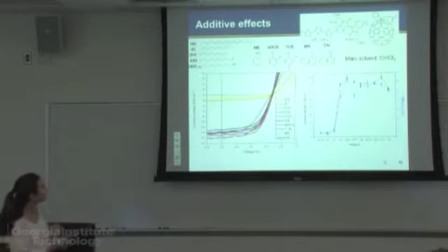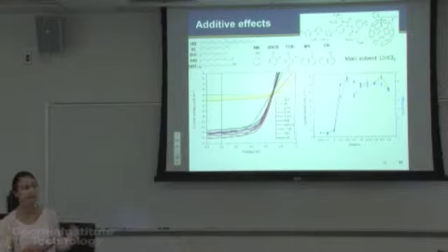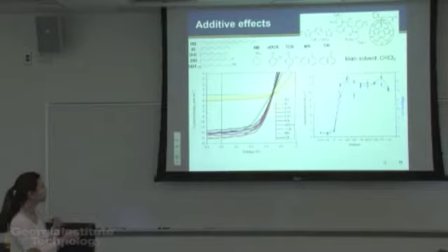And so what we did here was to look at one polymer-fullerene system that is cast from chloroform, and we add small volume percent of these different additives. And so you can see that structurally, these additives fall into two categories. Some of them are aliphatic additives, some of them are aromatic additives, and we can also change the functionality of the additives, looking, for example, at non-functional additives, monofunctional, and then bifunctional here.